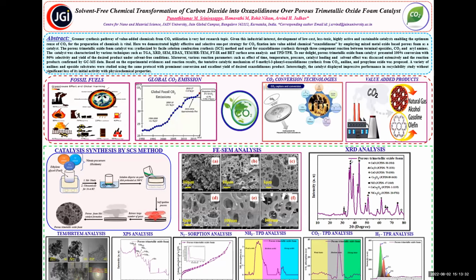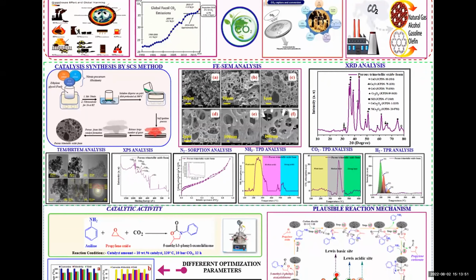After we perform the XRD analysis of the PTF catalyst, the XRD profile clearly shows a highly crystalline nature, and this profile clearly shows the formation of mixed metal oxides, such as copper oxide, cobalt oxide, nickel oxide, and less intense spinels of copper cobaltite and nickel cobaltite. TEM analysis clearly shows the PTF catalyst